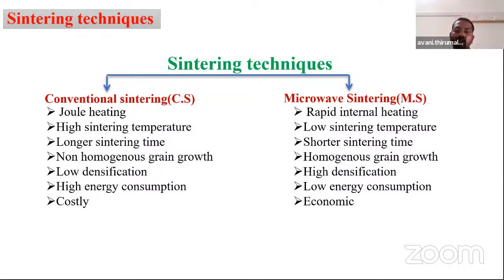For that purpose, we are concentrating on microwave sintering, and all the properties like D33 and dielectric properties and others will be enhanced with the help of microwave sintering. High densification will be improved in microwave sintering compared to conventional sintering. The reason is that in conventional sintering, the heat is dissipated from the outside to the inner sample. It will take some time. There is no uniform sintering. Porosity will be high in conventionally sintered materials.